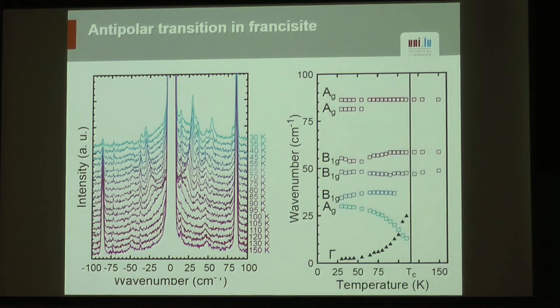Of course, you can do the usual fits of the Raman modes. These are the modes that do not move with the transition. And this is the soft mode here with Ag symmetry that goes down, and this is your damping that goes up close to the transition. So all this is very standard.